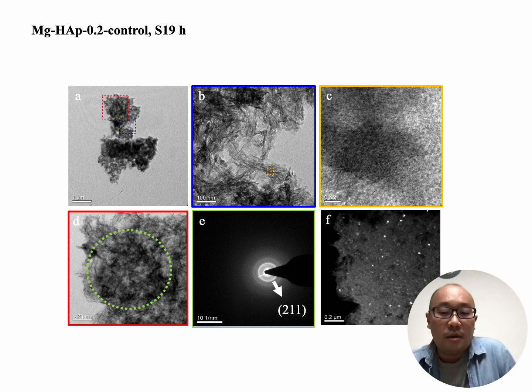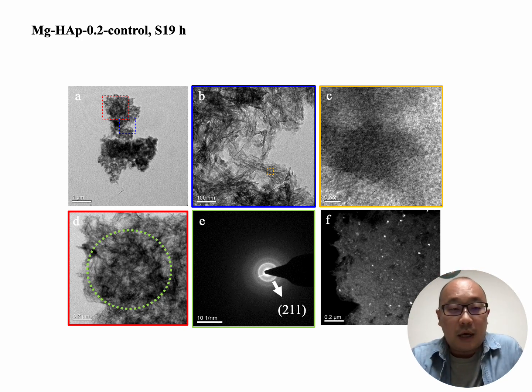And that's the TEM result for the 19 hour. For this region it is almost polycrystalline. Then the dark field shows different bright spots. It comes from one single crystal, but this whole region is polycrystal.